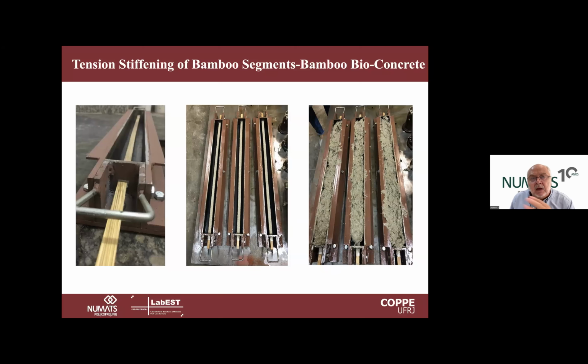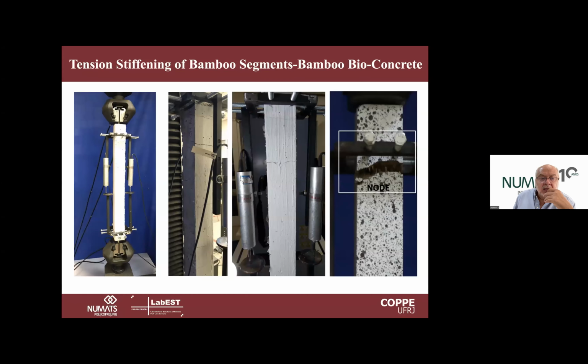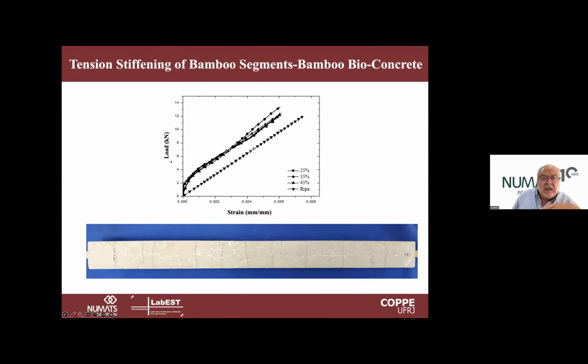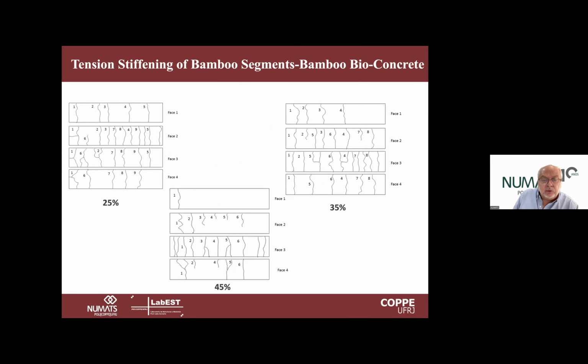Then, coming to the structural behavior, we did some tension stiffening tests. So we put one layer, one strip of bamboo inside the bioconcrete, and then we tension the element, and then we see the crack formation. So this gives us the tension stiffening mechanism. So you see here that when we put in bioconcrete from 25 to 45% of biomass, it doesn't change much, but mainly all of them show very fine cracks, a very well distributed cracking process. You observe the 4 phases of the element.